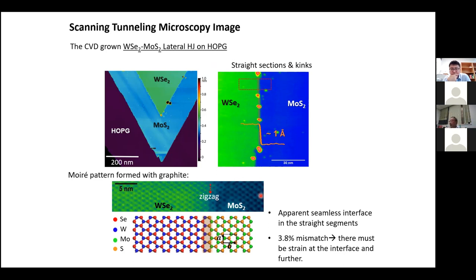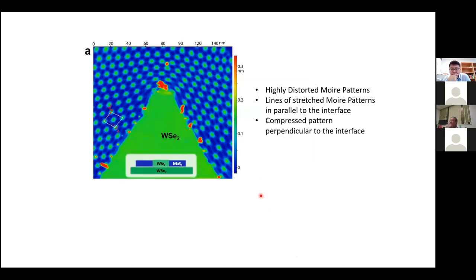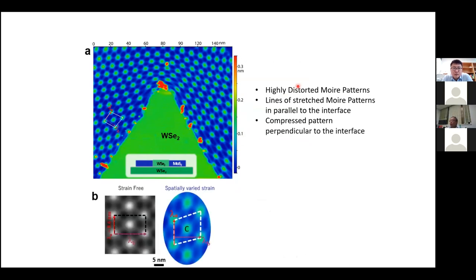So now let's look at this one. You have this MoS2, WSe2 lateral heterostructure. Sitting on the WSe2 here, you don't see a clear moiré pattern, but here the moiré pattern gets stretched. But the stretch is an amplification of the lattice mismatch. So by looking at the moiré pattern and comparing that to the strain-free one, we can actually determine the strain tensor here. The diagonal elements and the off-diagonal element can all be determined. The off-diagonal element, of course, is the shear strain.